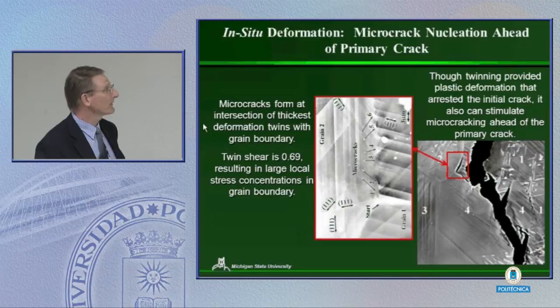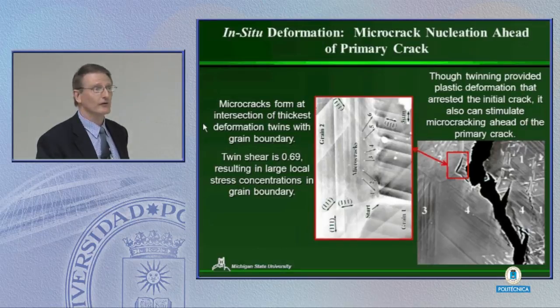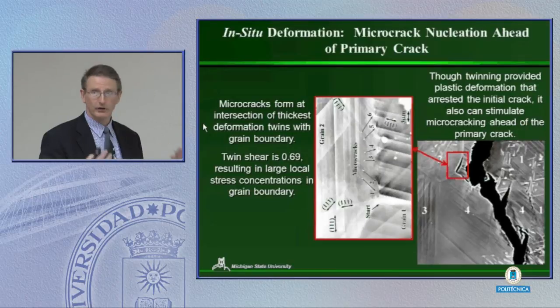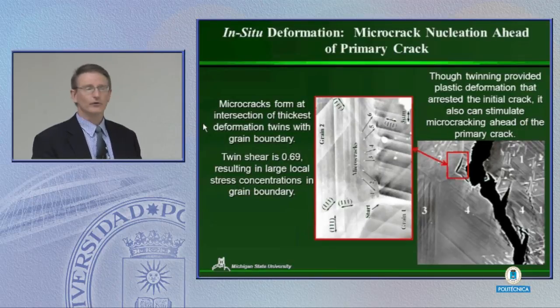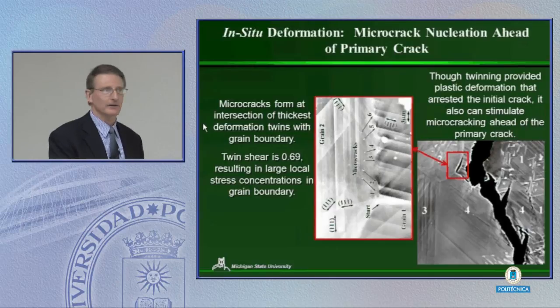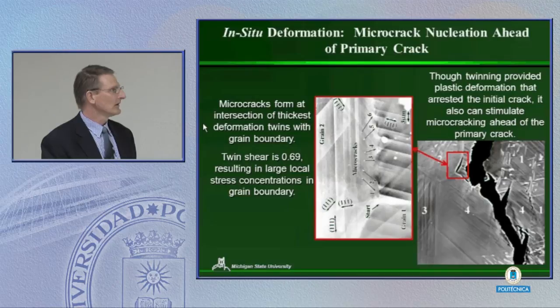And as we deform it a little bit more, we find that actually that boundary right there opens up into a larger crack. And so this is a mechanism where deformation is blunting the cleavage crack, but that deformation is also renucleating cracks further ahead. Okay, so we tend to think of deformation as inhibiting fracture, but deformation may also nucleate fracture.